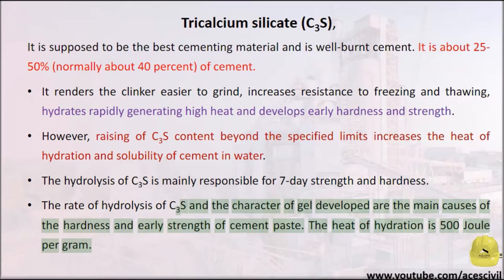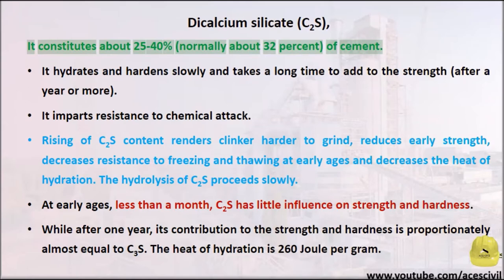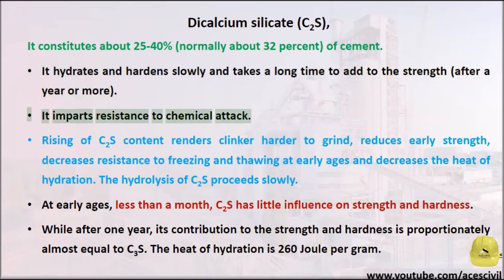The heat of hydration of C3S is 500 joules per gram. Dicalcium Silicate (C2S) constitutes about 25–40%, normally about 32%, of cement. It hydrates and hardens slowly and takes a long time to add to the strength, after a year or more. It imparts resistance to chemical attack.